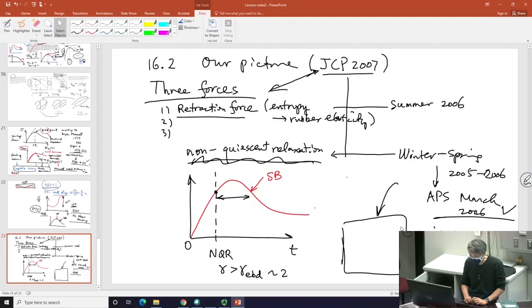And to see what's missing, there's nothing better than what I drew already here. Take a look at this startup experiment. You got a point where your entanglement no longer acts like a cross-linked sample. Since you don't have cross-linking, you only have entanglement. So it looks like entanglement is no longer active anymore, right? By definition. That's why you lose the ability to continue to be elastic.